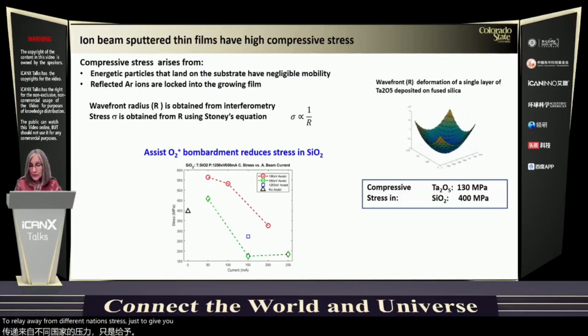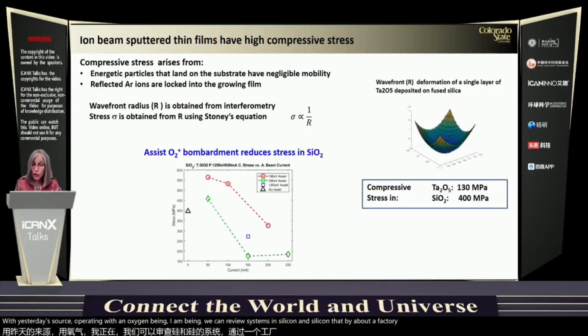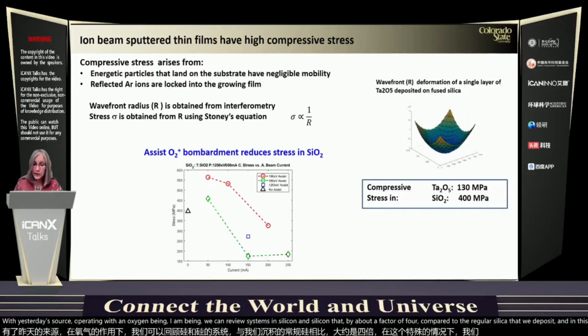Just to give you numbers, the compressive stress in tantalum pentoxide is of the order of 130 megapascals, and in silicon dioxide it is 400 megapascals. And so in recent years, we have been actively investigating how we can use the process to reduce stress. By bombarding the film during growth with the assist source operating with an oxygen ion beam, we can reduce stress in silica by about a factor of 4 compared to the regular silica that we deposit. And in this particular case, we use an oxide target.